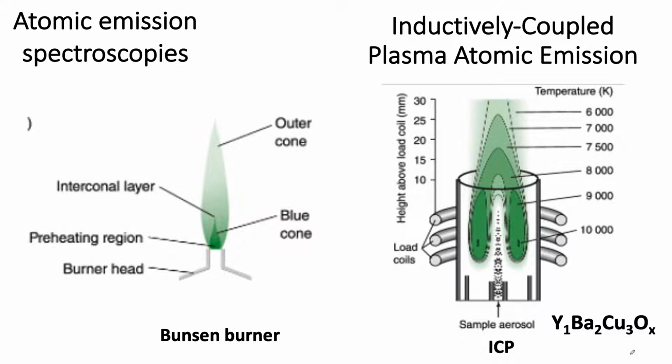All right, so I had a target, and then I had a way of making a film. And I mean, a film, it was very thin. You know, it was less than a micron thick, maybe on a 1-inch disc. I'd deposit onto a 1-inch substrate. And I needed to know the ratio of the yttrium to barium to copper, because it's supposed to be 1, 2, 3, but I could vary things, so it wasn't always 1, 2, 3. Right? So you had to tune it in.